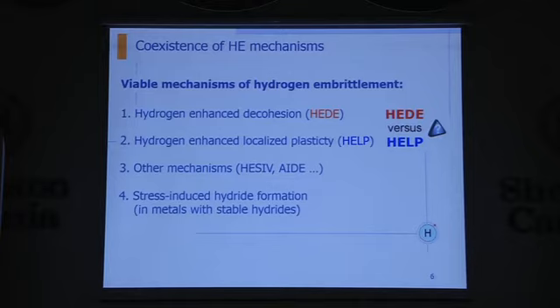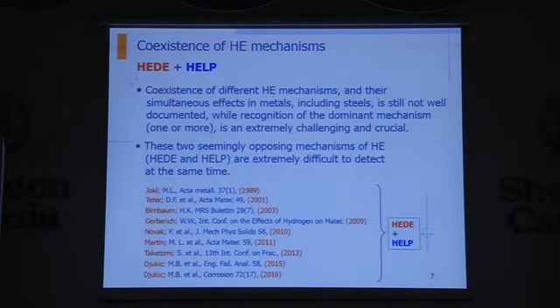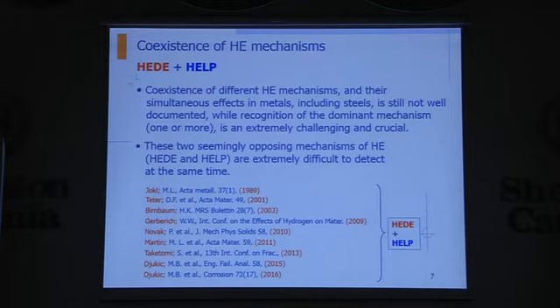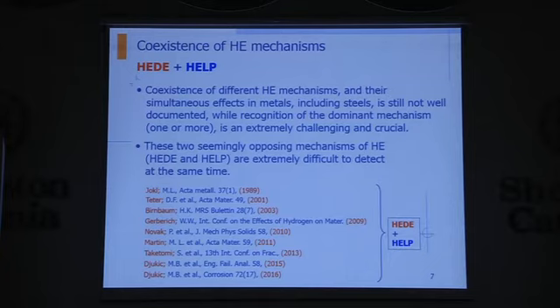There is debate between the HEDE and HELP mechanisms, and a large polarization of opinions in the literature regarding which one is dominant. It's very important to note that recent literature supports the co-existence of degradation and embrittlement mechanisms. Most of these models are based on modeling and simulation, while the recent ones are connected with real industrial components, where we prove the co-existence of these two mechanisms.